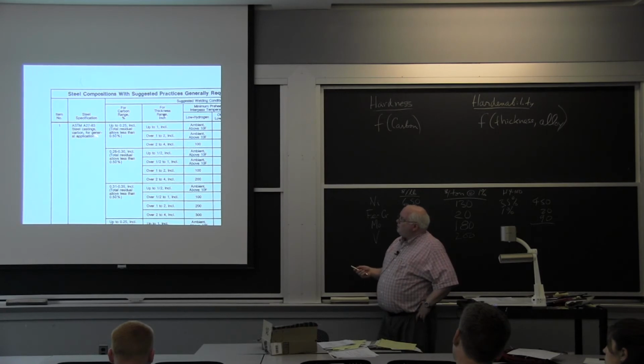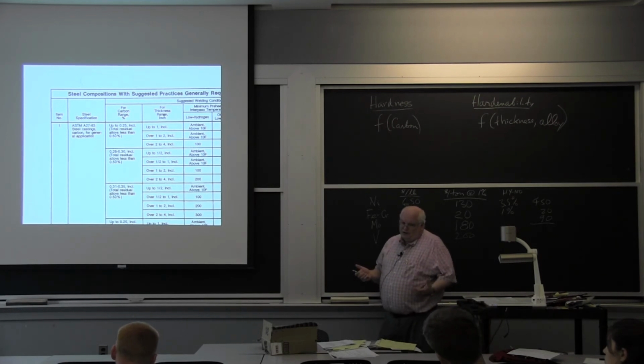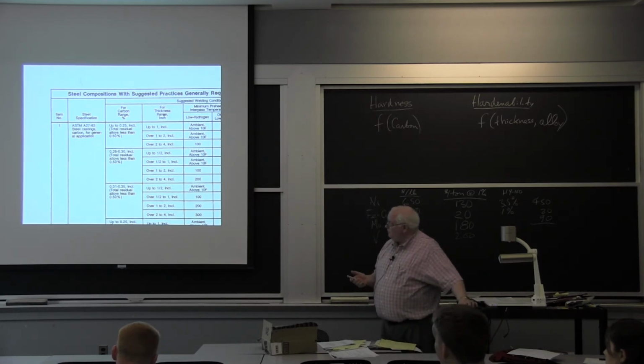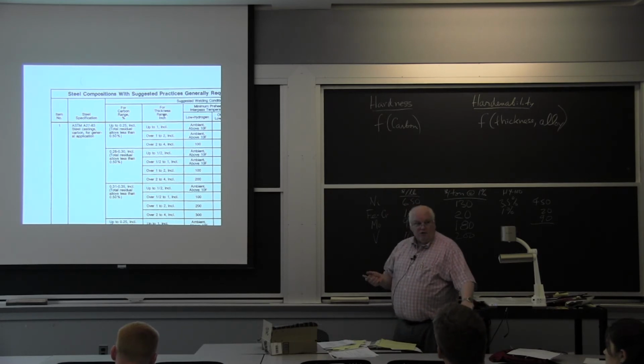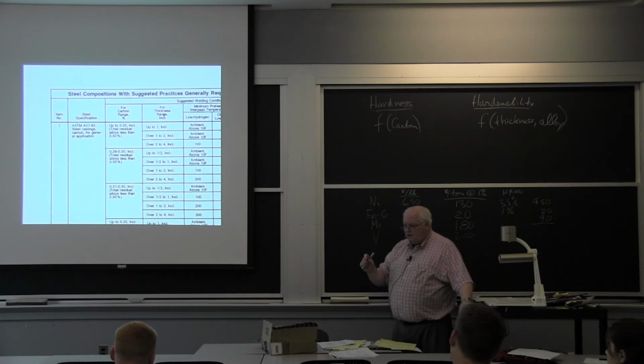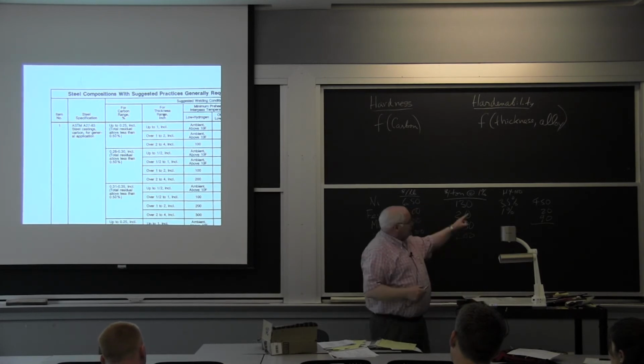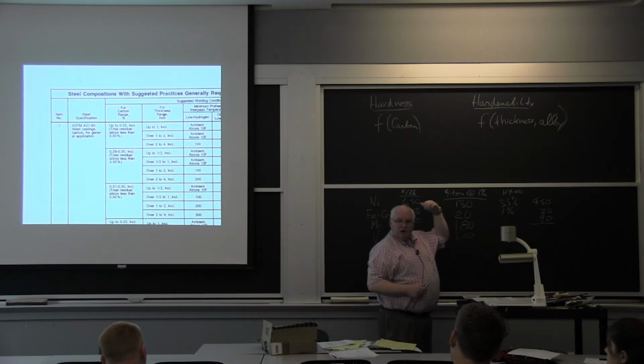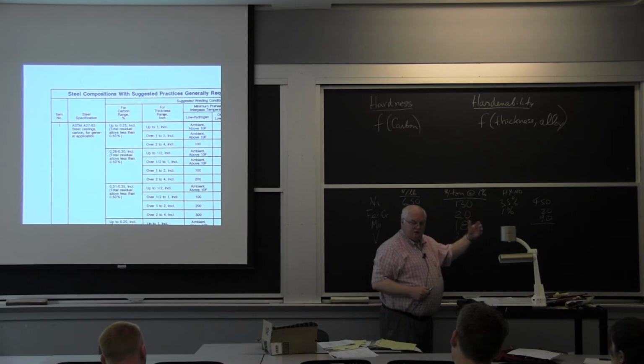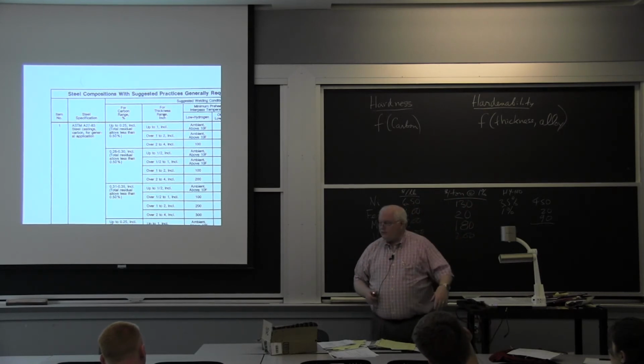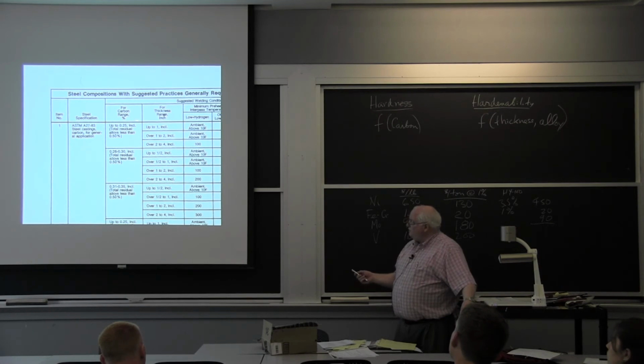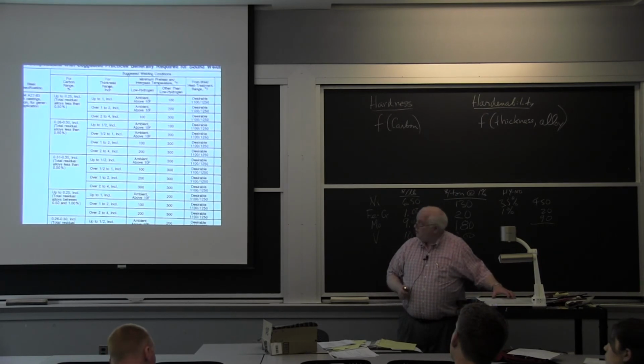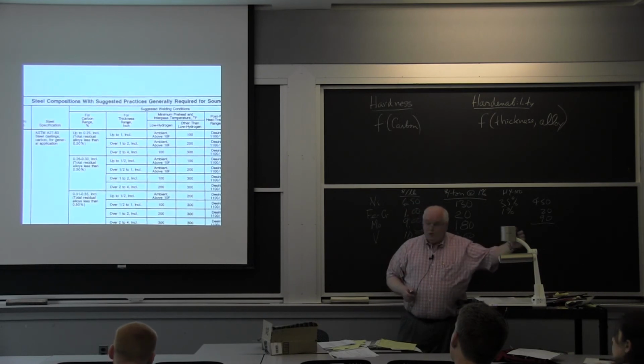Okay, well, I go to Stout and I try to find one of these 200 steels that matches, because we don't have ASTM specs back in the 1920s for this particular steel. But I tell them I need to know the chemical composition of the steel. So they get some little drillings out of the piece and they send it off to the lab and they bring me the chemical composition. And I say I need to know the thickness. Okay? So I need to know the thickness and the alloy content. And I also get the carbon content from the alloy composition. Okay? So I have hardness and hardenability on that steel. And I try to match it up to one of these 200 steels that's in Stout and Doty, and Stout and Doty's table here gives me the welding procedure.